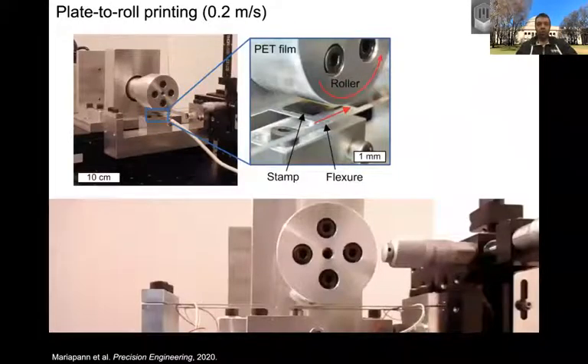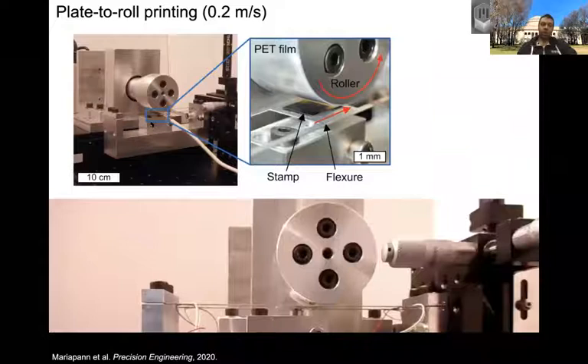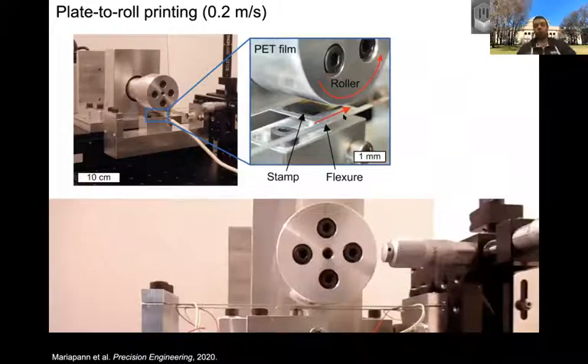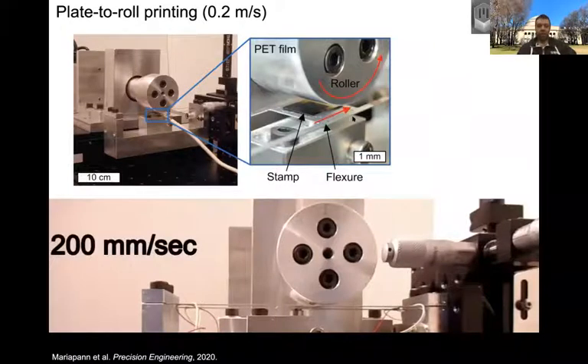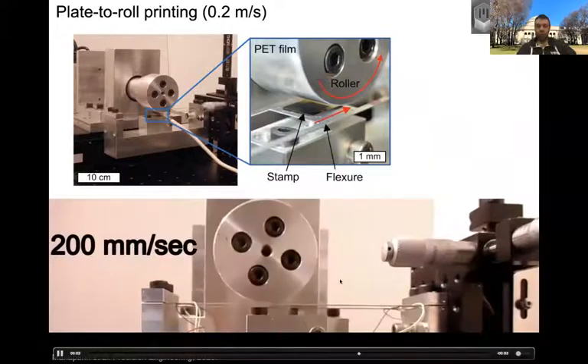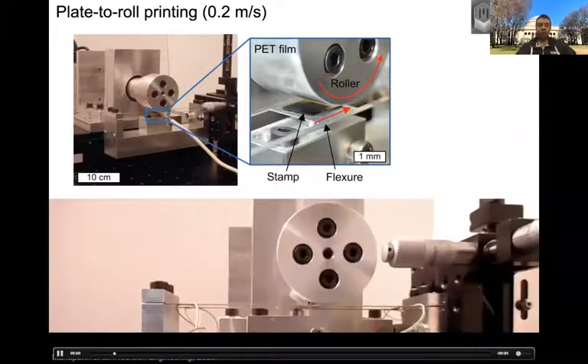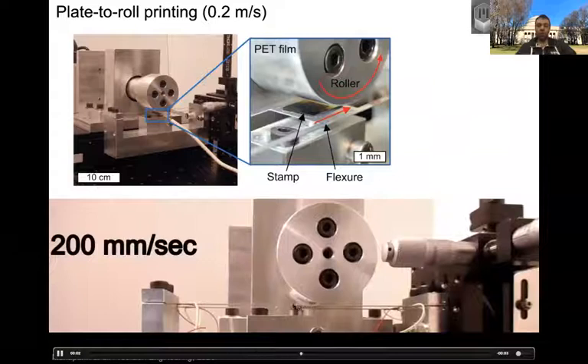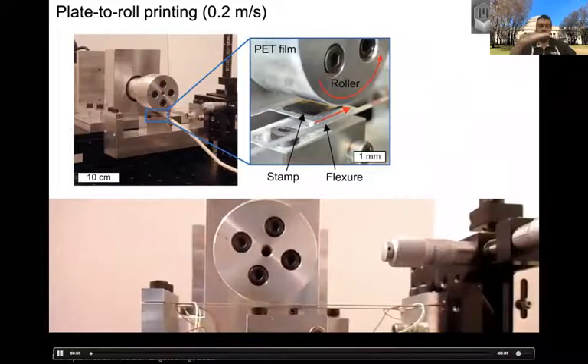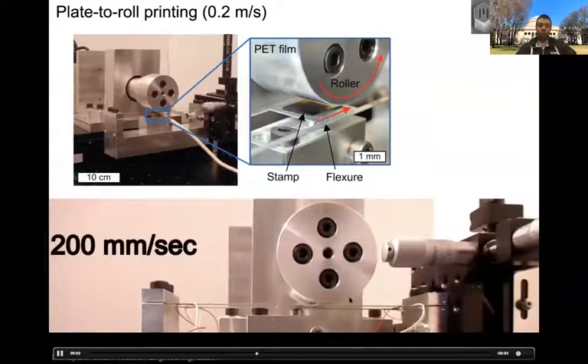We wanted to also demonstrate a sort of scale up. So we built a machine. Danush, who finished his PhD last year, built a machine and studied these mechanisms for plate to roll transfer. So in industry, you saw a roll to roll machine. We built a plate to roll machine where you only have one roller, but this gives the same kind of contact mechanics. And another very quick video just showing the roller moving laterally at 200 millimeters per second, where you're getting transfer of ink between a CNT stamp on this flexure substrate and the roller where we'd wrap the compliant substrate for printing.